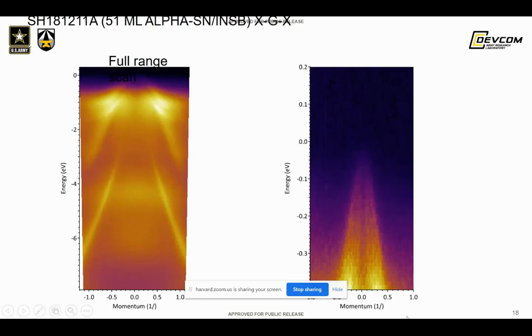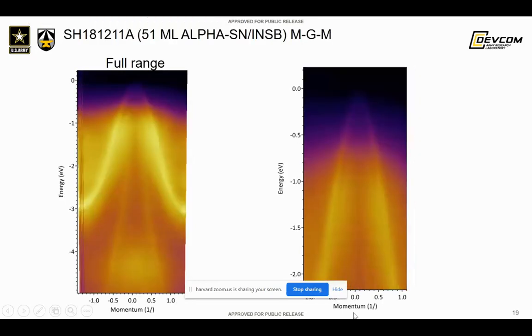If you go to lower energy, you can look at the top of the cone, you can see it a little better. Actually, the formation of it is getting closer to where the Dirac point is, but we didn't have enough. We need to dope the material to see this more clearly. And this is just showing data along a different direction, using the same thickness. We see the same thing basically.